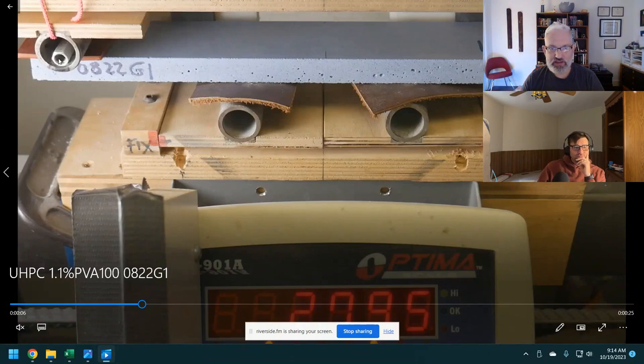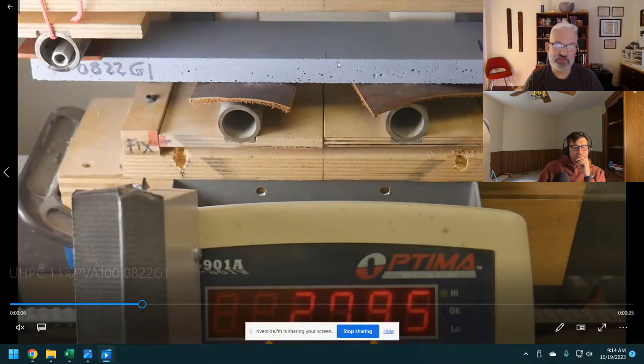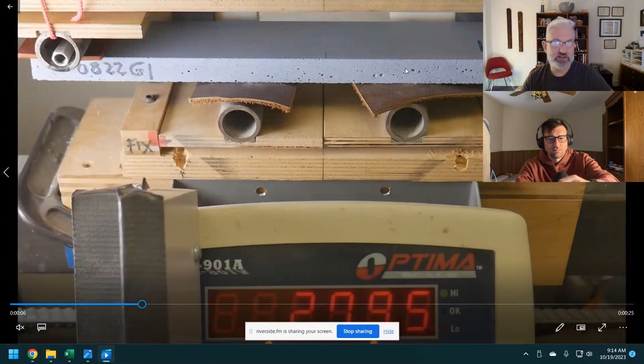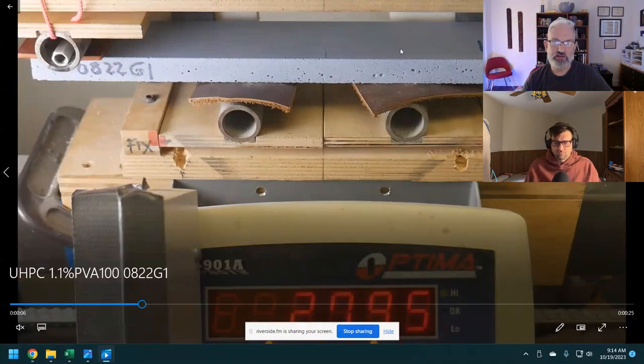In my test program, I make these essentially tiles, right? This is roughly 5/8 of an inch thick, roughly 16 millimeters thick. Of course, I measure the thickness extremely precisely. And this is a traditional UHPC mix, correct? This is a real world UHPC. I'm not calling it that because I want to impress people. This is from a technical paper. And it uses a 1.1% PVA 100 fiber load. The water cement ratio of this was 0.24.